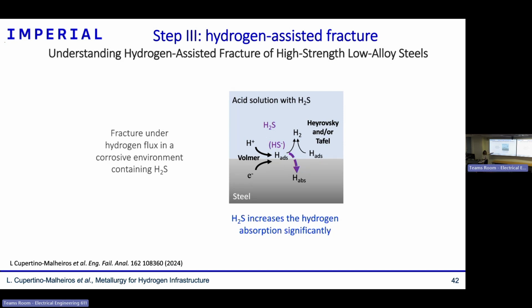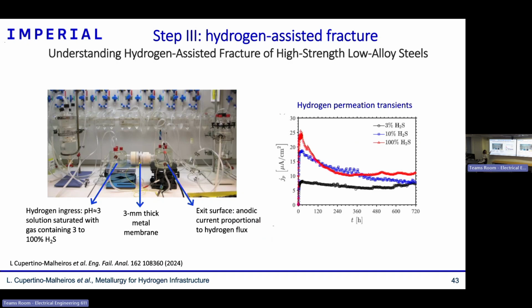The importance of this is also for the energy sector, it can be for oil and gas, but also geothermal. And this gas favors the absorption of hydrogen inside alloys. So when this gas is there, much more hydrogen enters. And as you know, hydrogen embrittlement is related to the amount of hydrogen. So now you get much more hydrogen embrittlement. All right. So to do that, I come back again to my hydrogen permeation. But now on this side, the charging side, we have acid solutions with H2S.